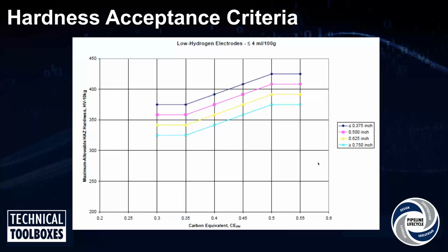So as you can see from this, if you're welding on thinner material, less than 3/8 wall, at a carbon equivalent of say 0.45, with low hydrogen electrodes, your acceptable hardness limit is over 400 Vickers, which is much higher than the 350 number that has historically been used. Again, on the other side, on the thicker material, the material over 3/4 of an inch, down to say a carbon equivalent of 0.35, your maximum acceptable hardness is about 325, again, which is less than that 350 value.